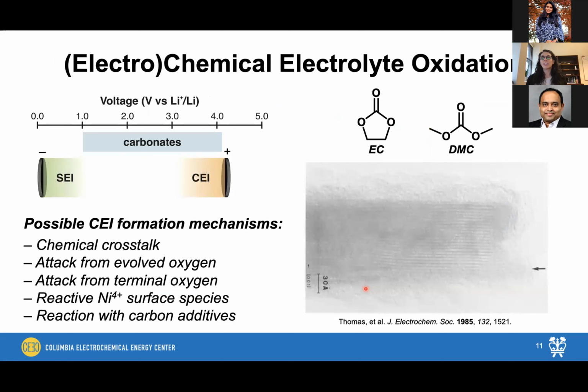From a fundamental perspective, actually understanding the origin of this cathode electrolyte interface is also quite intriguing. At the voltages that we are operating our lithium-ion batteries, we might not necessarily expect an interface to develop. So the interface on the cathode side of the battery is abbreviated the CEI, whereas on the anode side of the battery, we're calling it the solid electrolyte interface, which is abbreviated the SEI over here. So you can see from this diagram here, this blue bar represents the electrochemical stability window of our carbonate solvent molecules that we're using in the electrolyte solution.